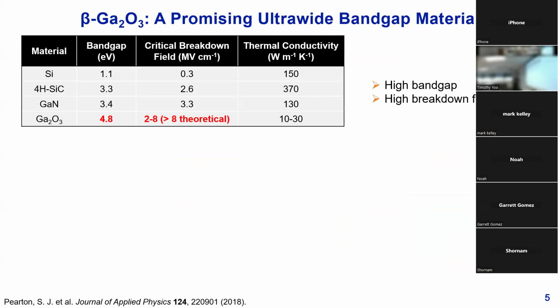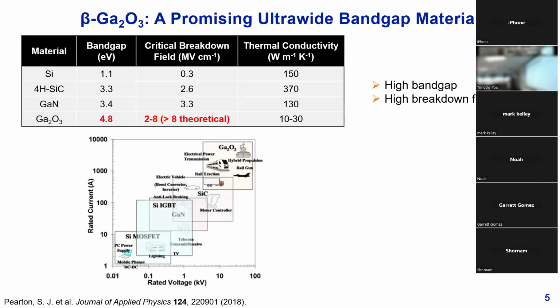It gets its name from having a much higher bandgap than other counterparts that we traditionally see, like silicon carbide, gallium nitride, and silicon. And this comes with a high theoretical critical breakdown field, over 8 megavolts per centimeter, with literature showing values of around 2 to 8. You can see from this graphic here that gallium oxide in particular fits a very special niche, ultra high power electronics, specifically in applications like high power transmission or heavy electrical vehicles.